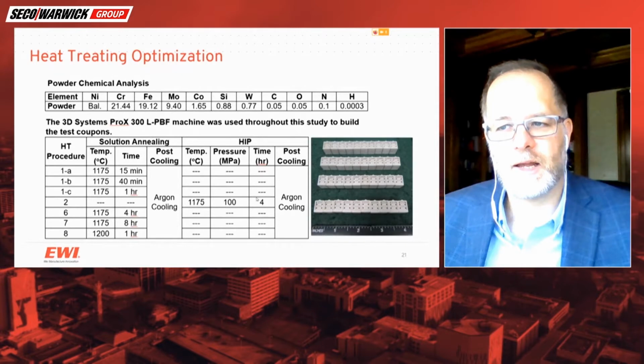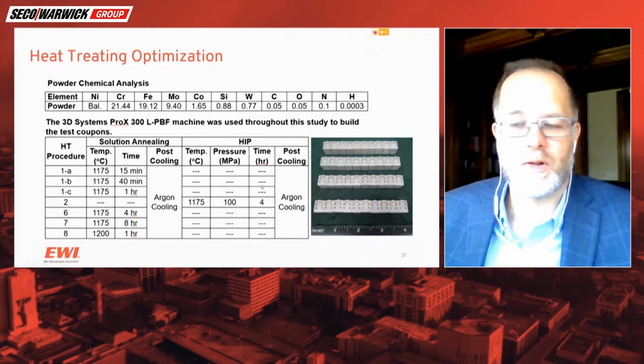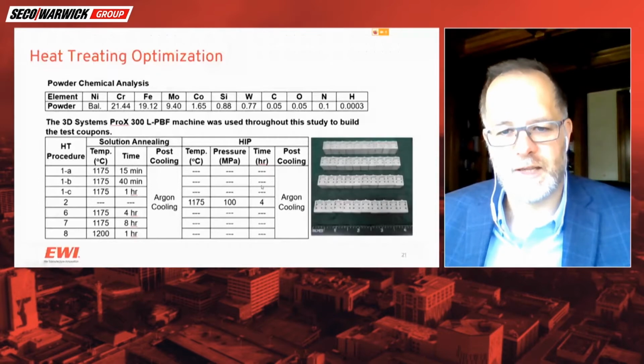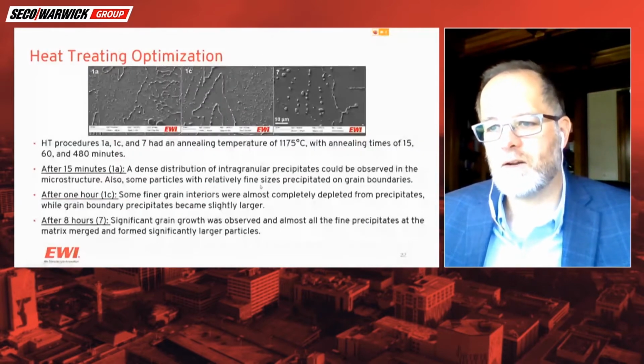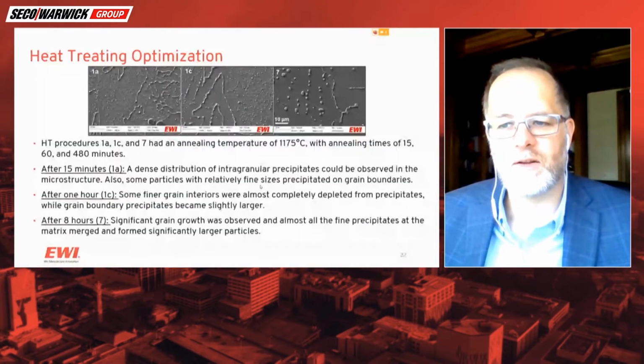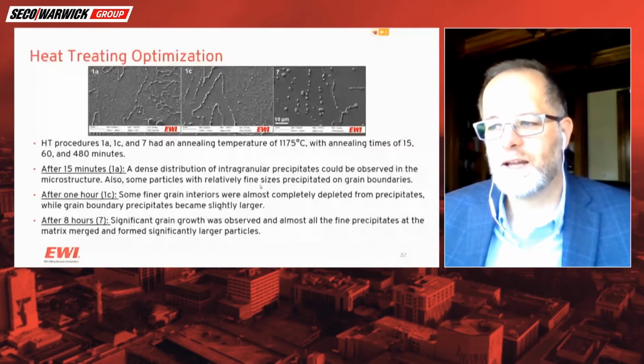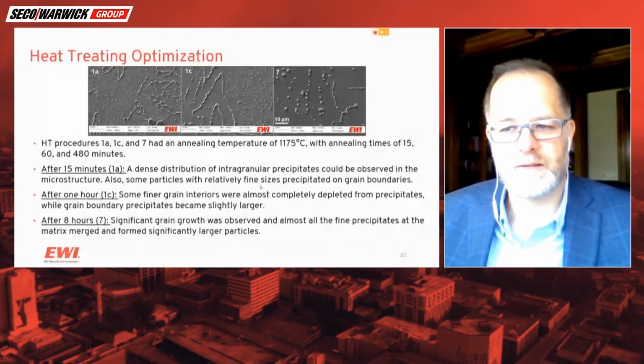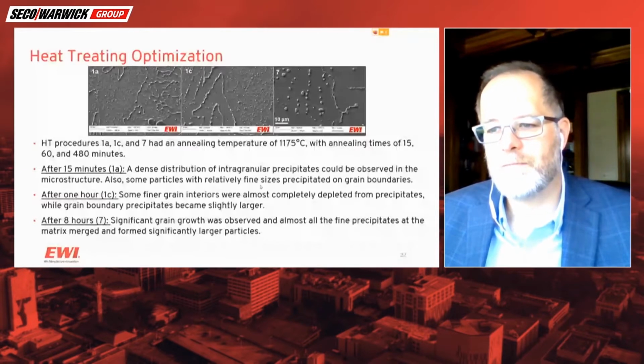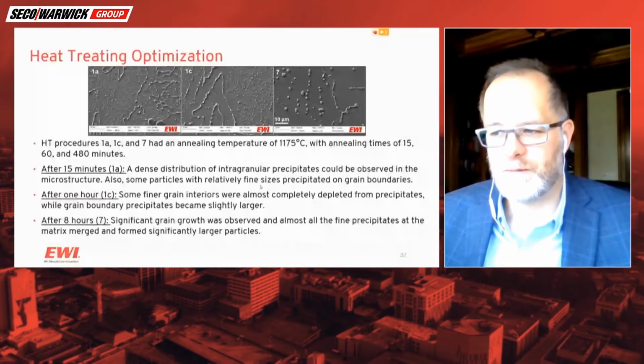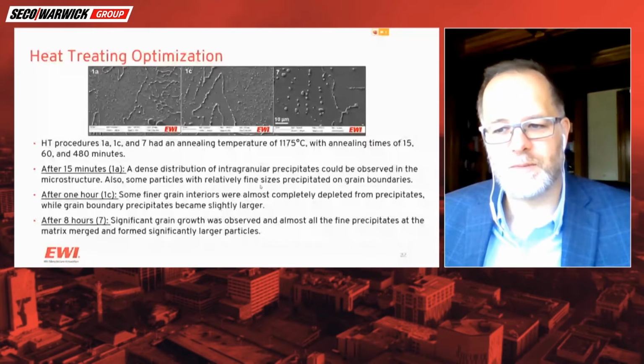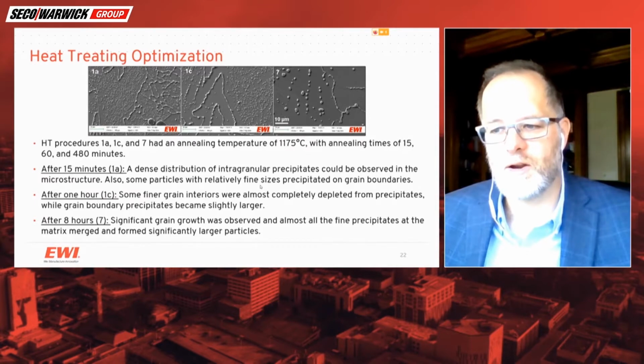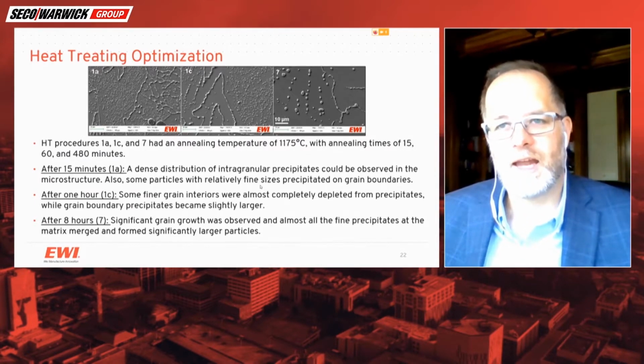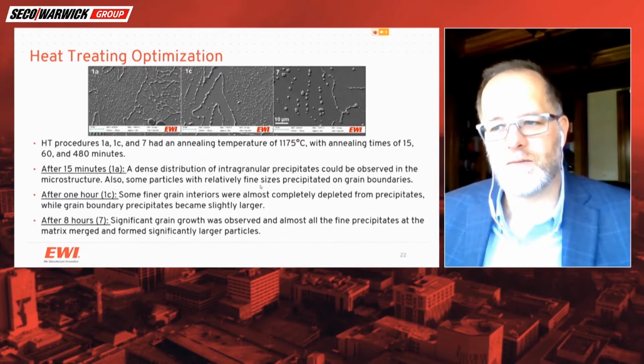And just a couple quick snapshots. There's a whole paper around this that I'm happy to send to you if anybody's interested. But you can see, this is just three different of those heat treat cycles. A 15-minute cycle, you get these intergranular precipitates observed in the microstructure. After an hour, the finer grain interiors are almost completely depleted, and then you're getting more of that grain boundary precipitates, and they start to get larger and larger. And then after the 8 hours, you got significant grain growth. And as you can imagine, each of these are going to give you different mechanical properties.